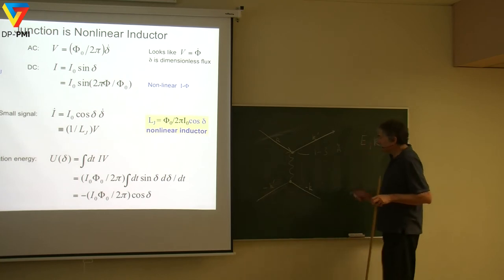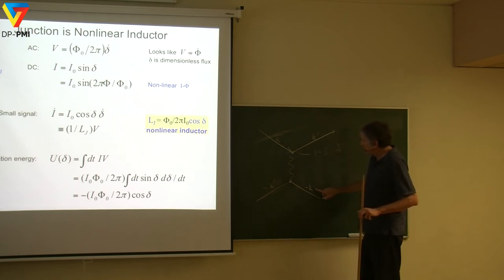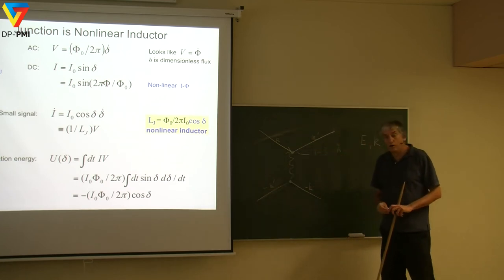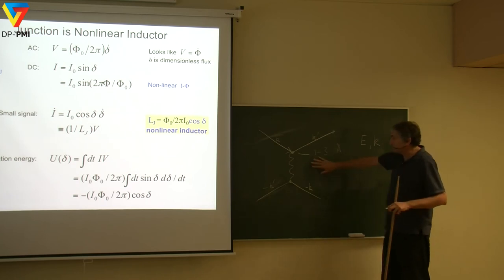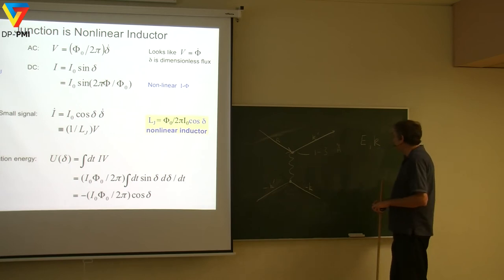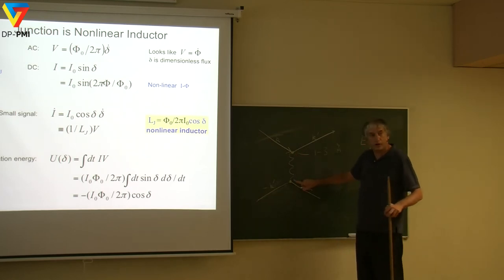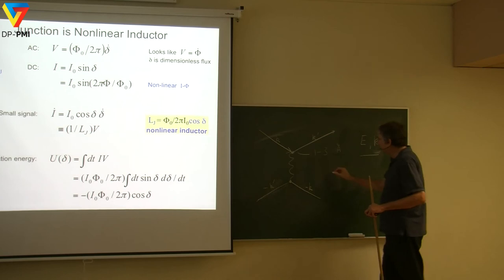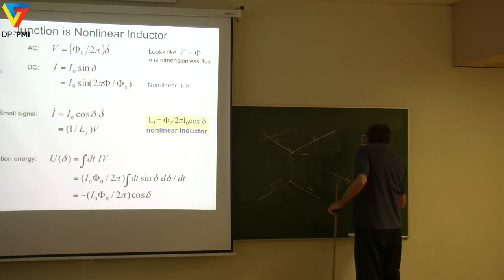Okay. Now, what's interesting about this is you know that this is K and minus K prime. This is K and minus K, and this is minus K prime and K prime. Okay, the initial and final states are going in the opposite direction, and this very easily conserves energy and momentum. You can see I've explicitly conserved momentum, and since you emit a phonon and absorb a phonon, it's going to conserve energy too. So because this is conserved naturally, this is really a big effect, even though it's second order.